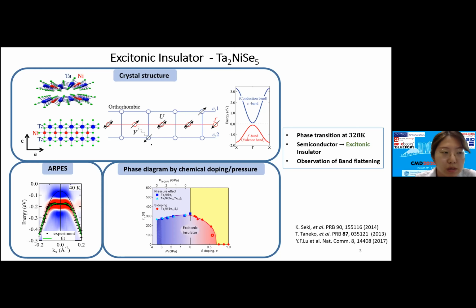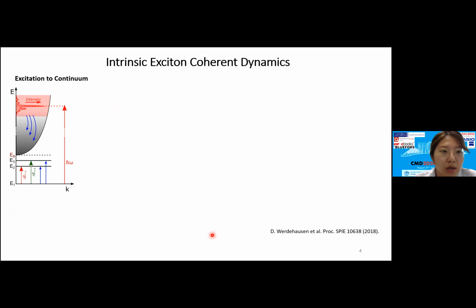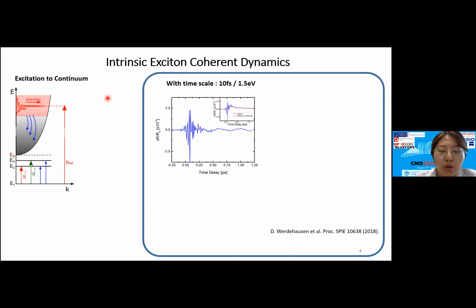So we started with an optical pump probe measurement to see the intrinsic coherent dynamics of the excitons. We pumped into the continuum, which means far above the energy band gap of the system. In principle, we need a pulse length of 10 femtoseconds for the measurement, because our system has a band gap of 160 millielectron volts. So this is the result.